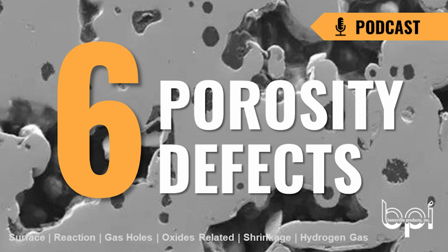Ernie brings up a good point. When you're looking at porosity, look at the location and that will help you determine what kind of porosity it is. One more thing on this slide, the oxides show up as surface porosity, but they're not really porosity until you machine the part. The oxides will be hard and they'll tend to tear. So when you're machining, if you're having a lot of rejects on the surface, those typically are oxides. They'll pull out during the machining process.